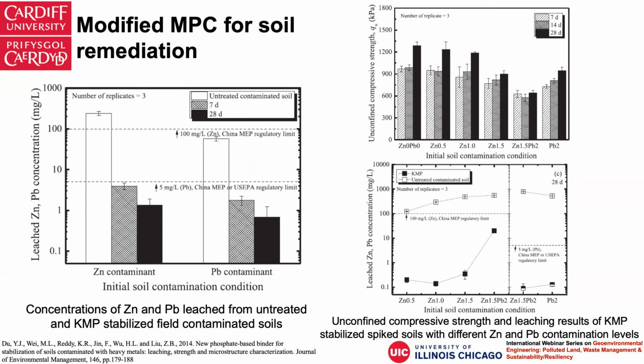So using reactive magnesia, we can get the stabilization of solidification very quickly. And then the slow-releasing phosphate ions from the rocks contribute to the long-term effectiveness. So that works quite well for heavy metals like lead.